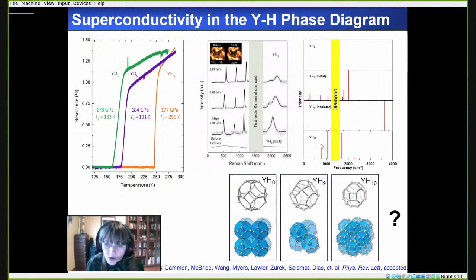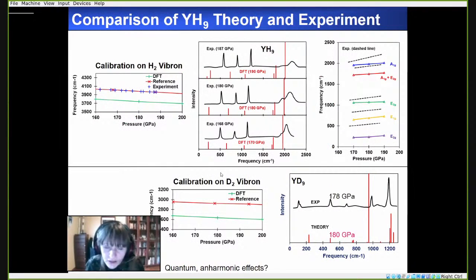So YH9 or YH10 are possibilities. However, the peaks are a better match to YH9, which is therefore why we characterize this species to be YH9. Moreover, the volume is in better agreement with experiments, and we believe that the TC is also in good agreement with what was measured and what was theoretically calculated.